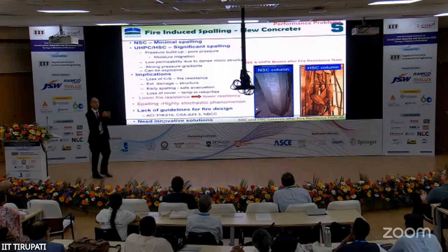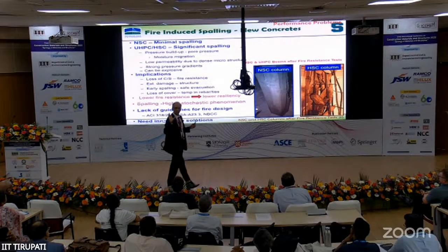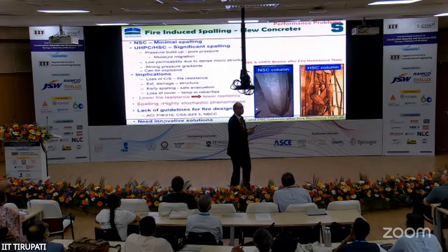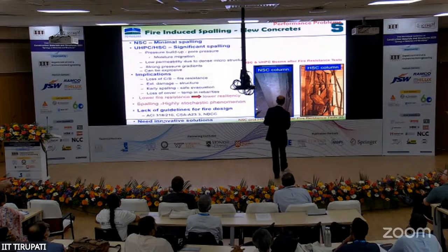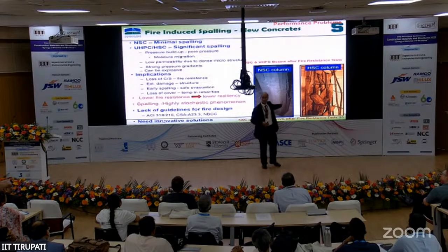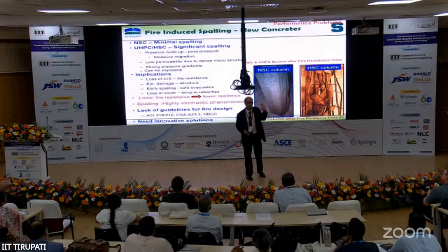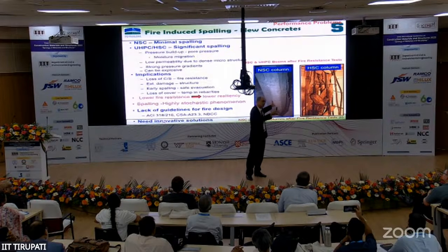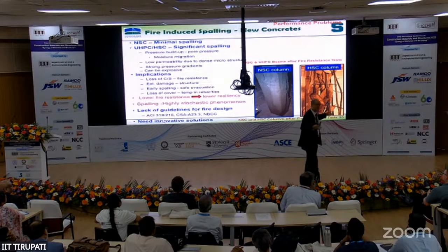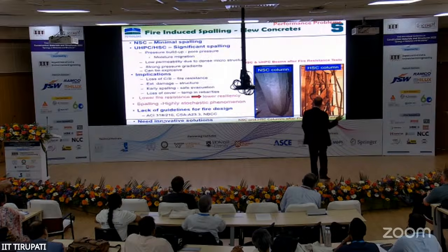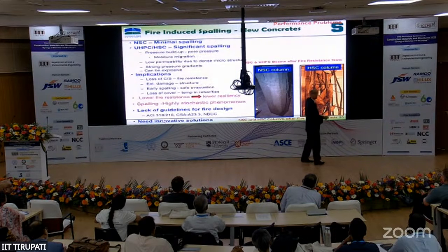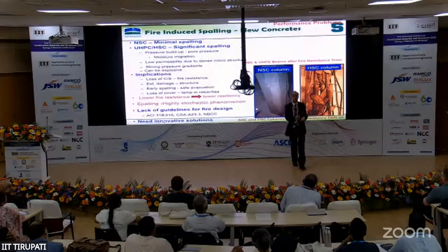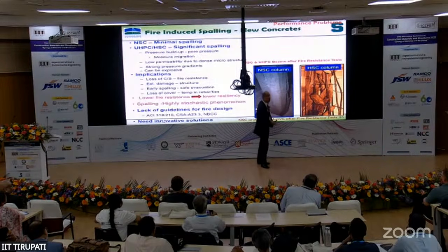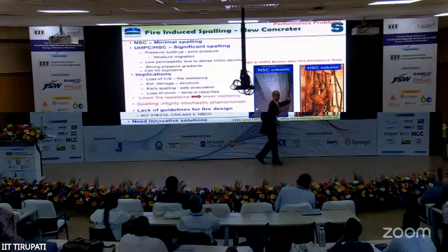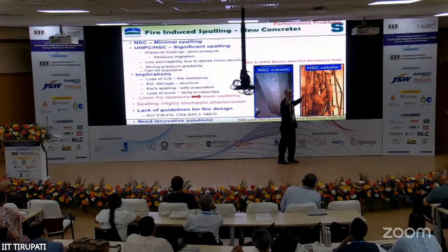And these concretes always have water. Maybe it's a reduced amount of water. What happens? A conventional column, normal strength concrete column, can you see here? After 3 hours, nothing happens. High strength concrete, I almost call it UHPC, is 140 megapascals, and doesn't have steel fibers or anything. Tests on 140 megapascals concrete were done for the Portland Cement Association. So water becomes steam. Here your permeability is 10 to the power of minus 16. It's about 10 to the power of minus 18 or even up to 19. It's hard to measure those.